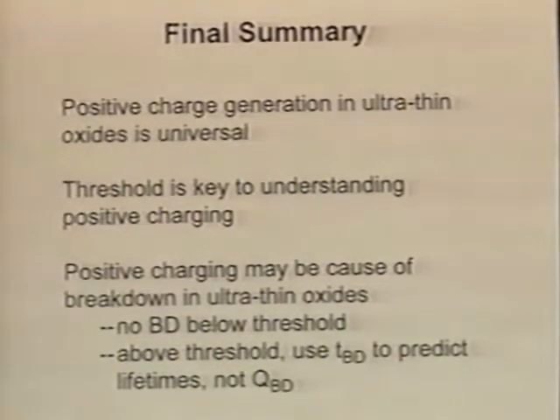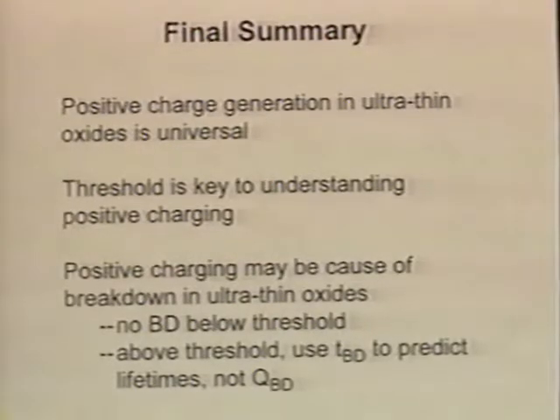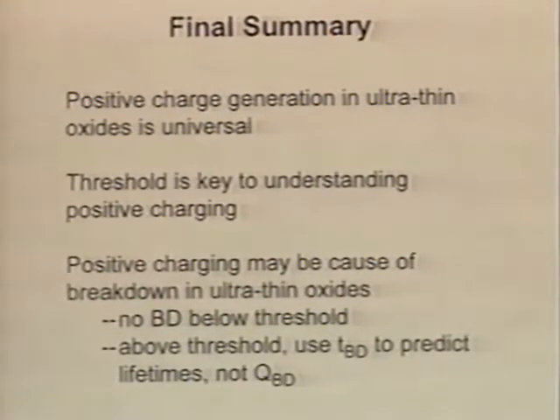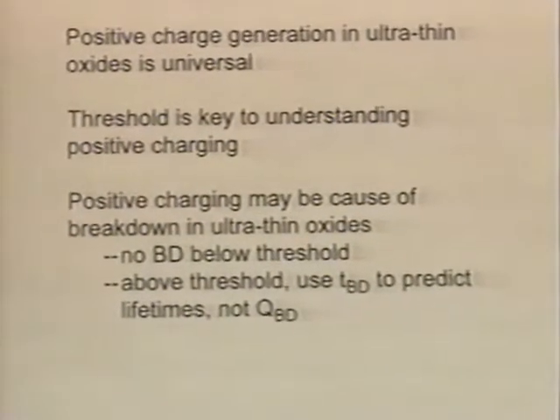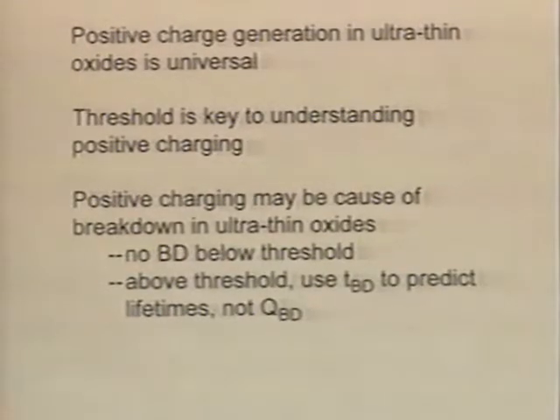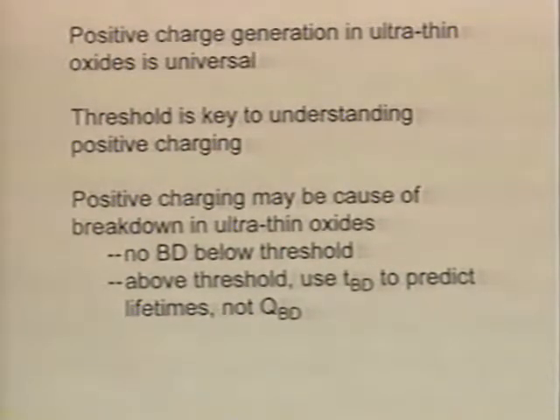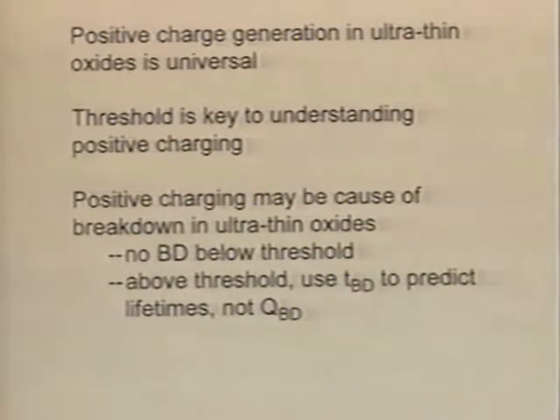And I think it's the principal degradation effect in ultra-thin oxides. And I believe the threshold is a real key. Understanding that is a real key to understanding the ultimate nature and origin of the positive charging. And finally, positive charging may be the cause for the final breakdown in ultra-thin oxides. The exciting news is that there's no breakdown below this threshold, and this opens up a wide opportunity for coming up with devices that you want to have a very long lifetime.